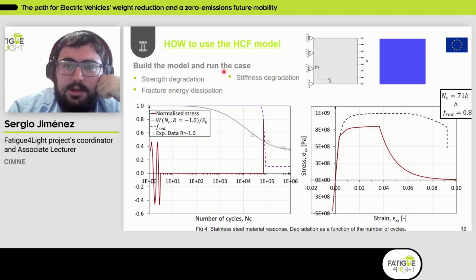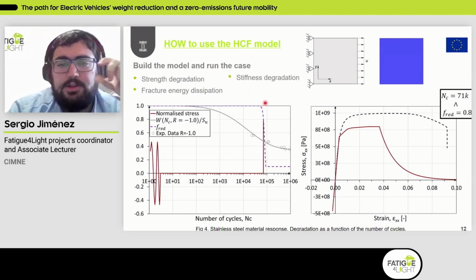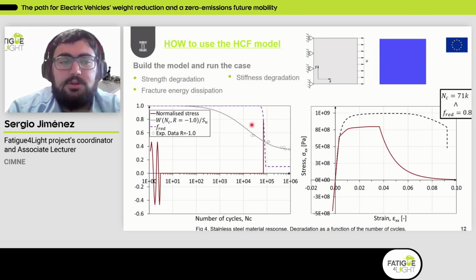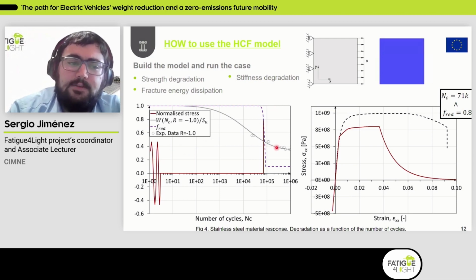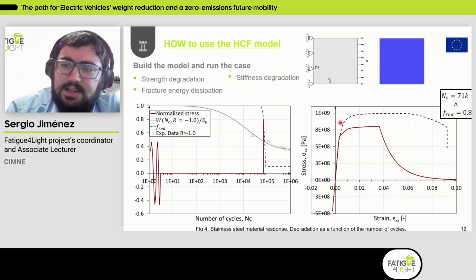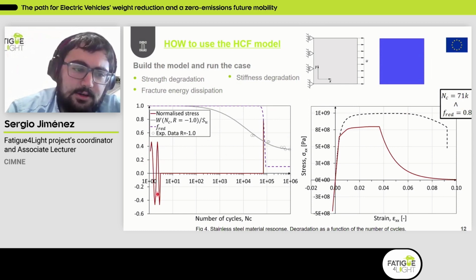That's it. So just to exemplify this, I've just prepared a small example in which I'm introducing a cyclic load in the material, and then after a few cycles, we move towards a monotonic load. And through this type of example, we will be able to see this strength degradation, fracture energy dissipation, and stiffness degradation processes that can be captured through this high cycle fatigue model. So in this first case, what you can see here is that we are applying 71,000 cycles of this cyclic load, showing the normalized stress.